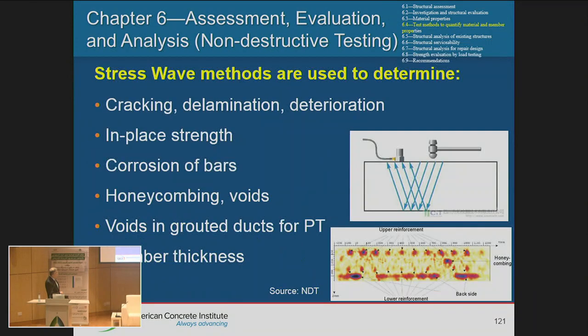You have the stress wave method, where you have the input here and the receiver here, and that will give you an indication of the approximate in-place strength, whether you have corrosion in your bars or not, whether there are any voids or honeycomb voids, or the member thickness.